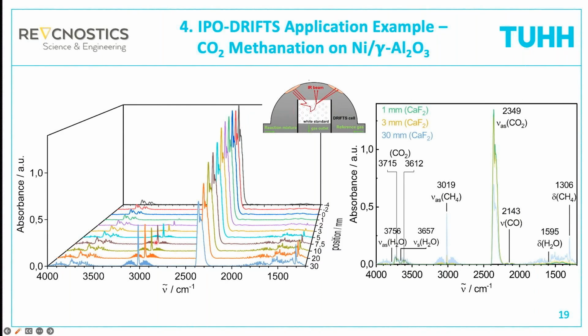Then we see here the asymmetric stretch vibration of methane. It's, of course, formed. You can see how it goes up. These are the rotational side bands. Then here we have some combination bands of CO2, and we have the asymmetric and the symmetric stretching vibration of water. Down here we have also deformation vibrations of water. We have deformation vibrations of methane. And if you look very closely here, you have a little bit of a shoulder of carbon monoxide. Now, this is some CO that is formed by reverse water gas shift reaction.